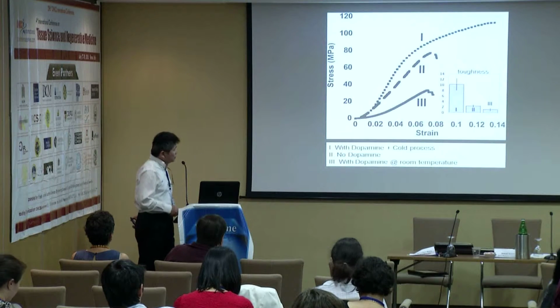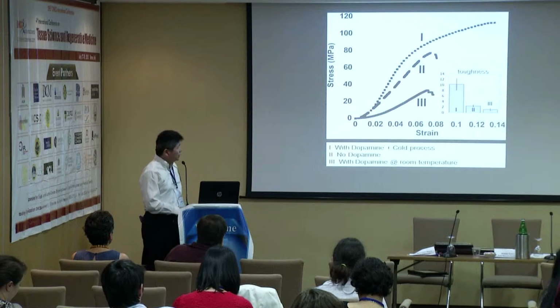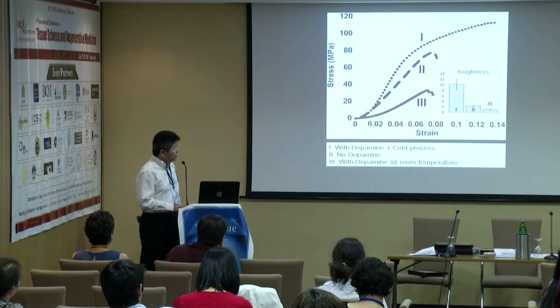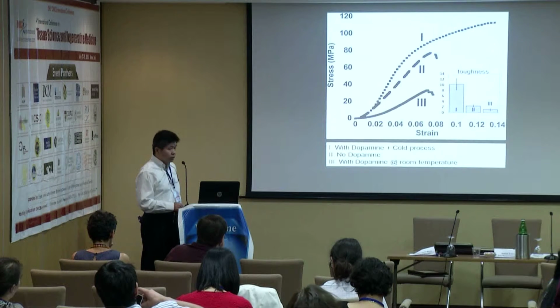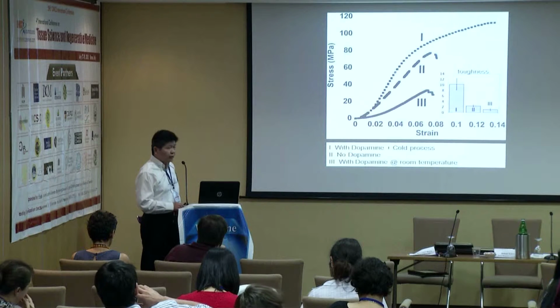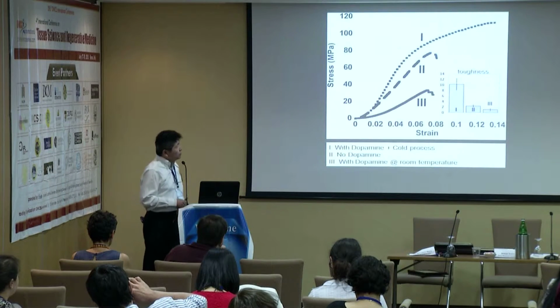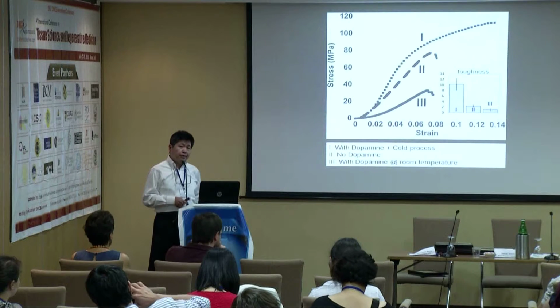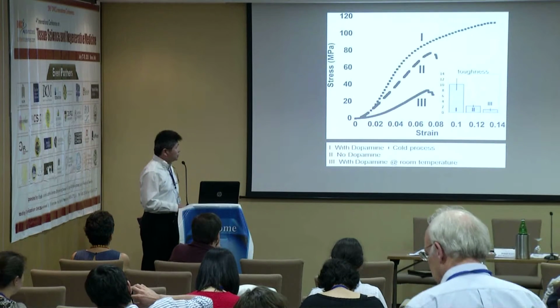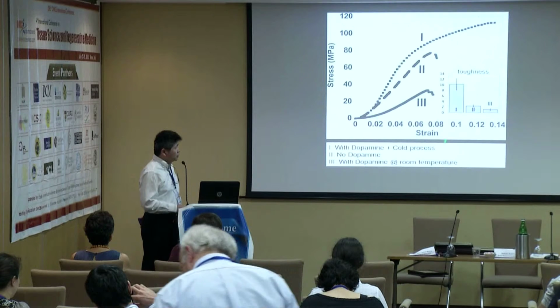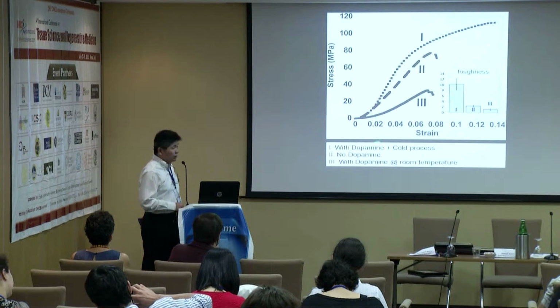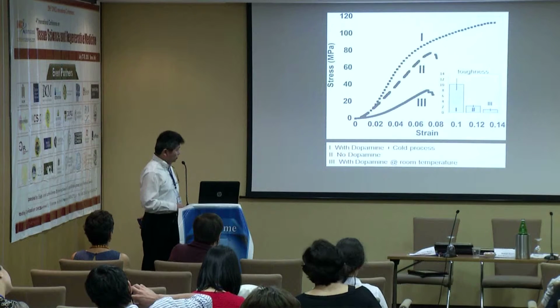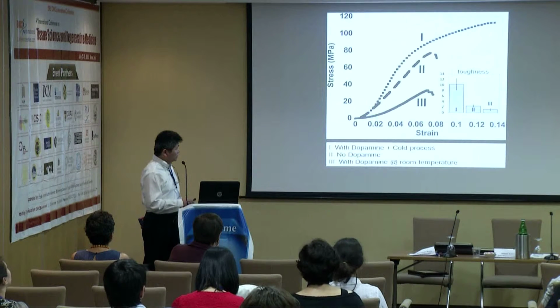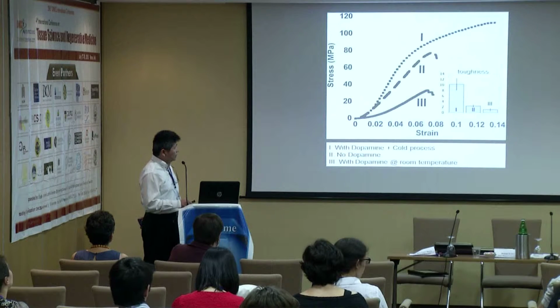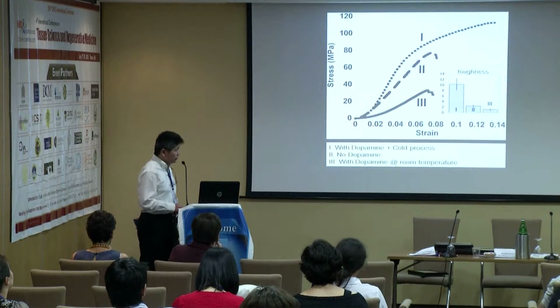So this is when we started using dopamine in the system. In the beginning, we used dopamine, but we made our material at room temperature. And we found that the mechanical strength did not increase, instead it dropped from 2 to 3, which is a dramatic drop. And we spent about a year to figure out why it happened. Then finally we found out that in our system, we do need to suppress the sol-gel reaction and let the dopamine reaction go through first. So therefore we use the processing in number 1, which increases the mechanical strength and also increases the toughness of the materials.